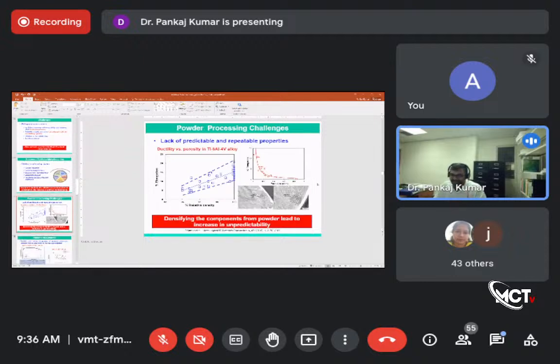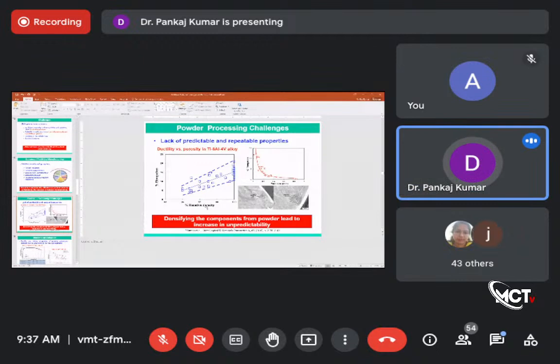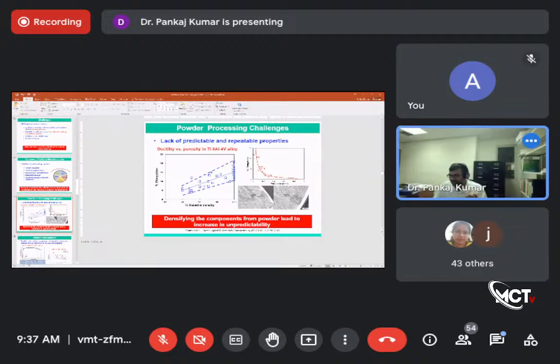Okay, so where does reliability come from? If you talk about powder-based technique, right? In the powder-based technique, reliability is an issue, and that issue is not new. That issue has been there for a very long time. Okay, so whenever you use powder-based technique, this is the thing you will see. So this is an example for the titanium alloy, titanium 6 aluminum 4 vanadium. And if you look at this diagram, percentage elongation versus relative density, right? In additive manufacturing technique or any powder-based component, what you want is the highest density you can have. You always have residual porosity, right? But you want to be very close to the theoretical density.